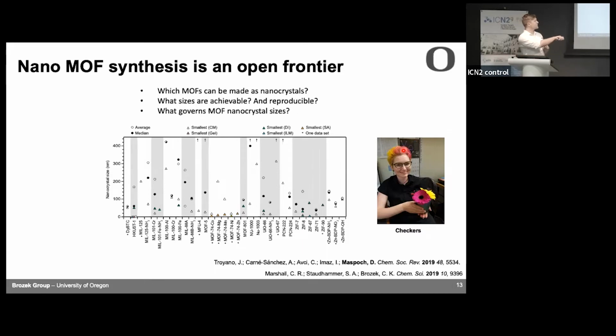Of the 100,000 or so known MOFs, it's only about these 20 or 30, and many of them are actually structurally related to each other, that have been reported as nanoparticles. Anything that's a circle is an average or median size, and anything that's a triangle is the smallest size. What you see when you look at this is that these sizes aren't actually that small. Most of them are sitting in the hundreds of nanometers.